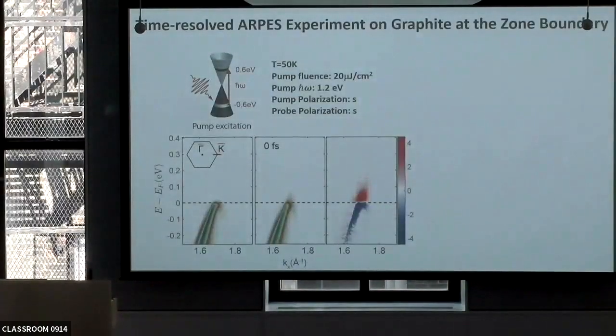So here are the data. These are the data that Katie has already shown. You have data measured at the corner of a Brillouin zone. Here you have the chemical potential, so electrons are below the chemical potential, and here you see the Dirac-like dispersion. You don't see one side of it due to cross-section issues. And then you start pumping, so 0 femtosecond is when pump and probe pulse are coincident, and well, there is a faint hint of intensity here.